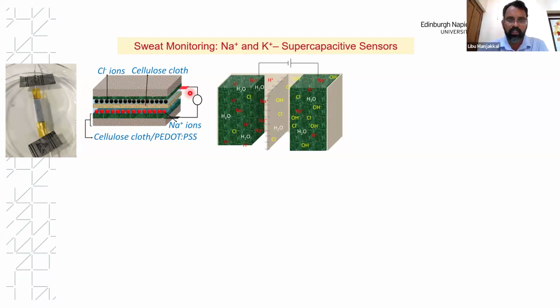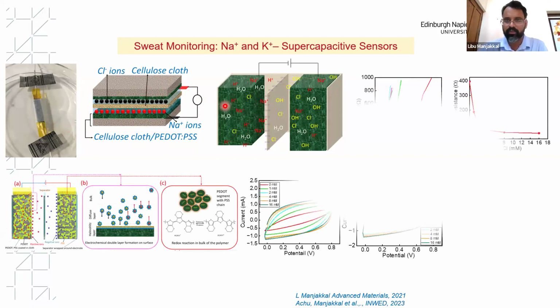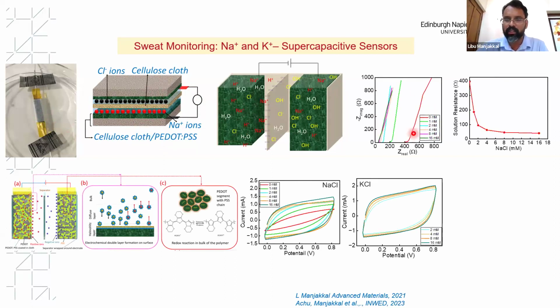So what we did was, on top of a cloth, we coated PEDOT:PSS as a conductive material, and then we converted the cellulose cloth into a conductive cloth. With various sodium variations in the human sweat or a sweat-equivalent solution, we monitored the performance. As you can see from here, by varying the sodium concentration in the solution, the resistance and the impedance vary due to the conductivity variation of the solution, and it's like a straight line, and the impedance is like a Nyquist plot.